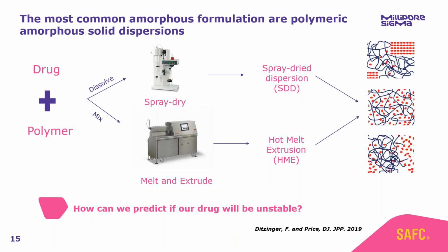In this example, we may see a slight increase in the dissolution rate, but we will not see the amorphous solubility advantage. So we will no longer generate that supersaturation. So this is a big issue, also from a long-term stability perspective. If we have an amorphous formulation on the market, we have to be absolutely sure that we will not see such phase separation and recrystallization across the shelf life of the product.